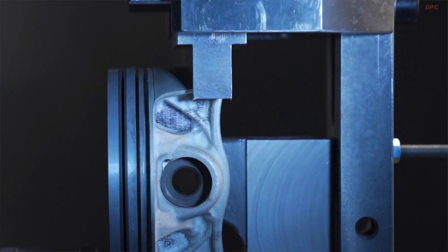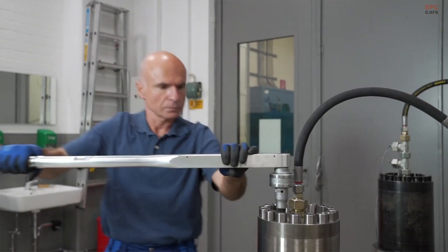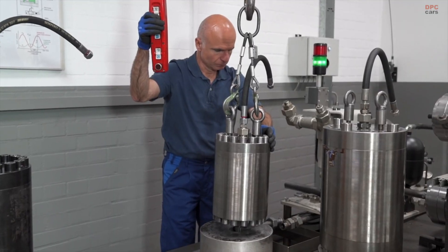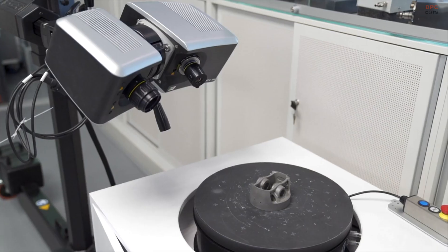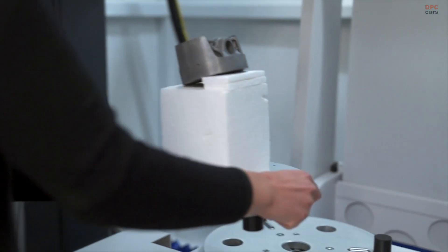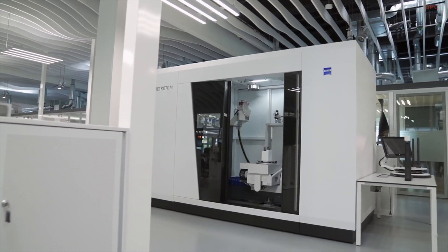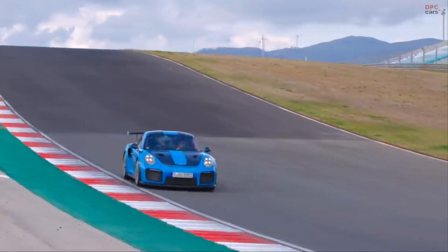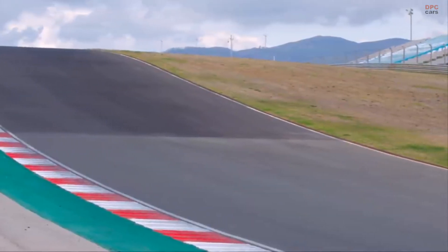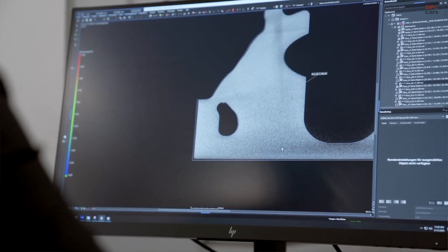The advantages of this technology are striking. The new piston design includes a cooling channel that lowers the piston's temperature by more than 68 degrees Fahrenheit. Additionally, the pistons are 10% lighter than the standard versions used in the 911 GT2 RS, while being stronger and more rigid. These improvements allowed Porsche to increase the power output of the GT2 RS's already impressive 700 horsepower twin-turbocharged 3.8-liter flat-6 engine by an additional 30 horsepower, with the added bonus of enhanced fuel efficiency.